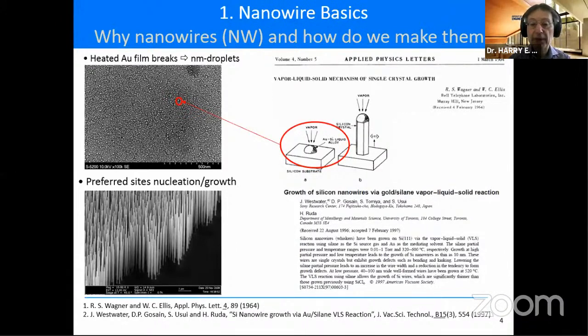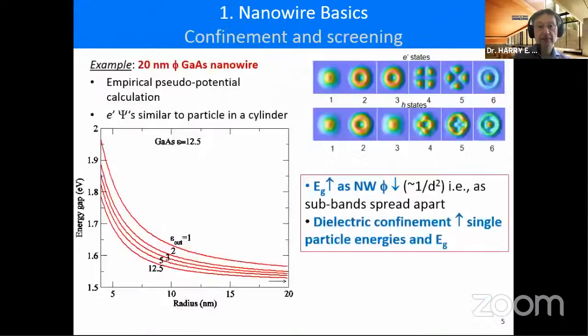And since the catalyst has not been consumed, it can effectively go on indefinitely, the wire growing, using that intermediate liquid phase to mediate between the vapor and the solid, hence vapor liquid solid, and get growth. And in practice, how we do it is, if you look on the left micrograph top, you'll see a thin film of gold, a few nanometers, has been heated, and it self-assembles into islands of gold, from which, for example, if it's indium antimonide or indium arsenide, those adatoms are absorbed in those droplets, and the growth beneath, which shows those nanowires growing effectively indefinitely, occurs. So that's the growth process.